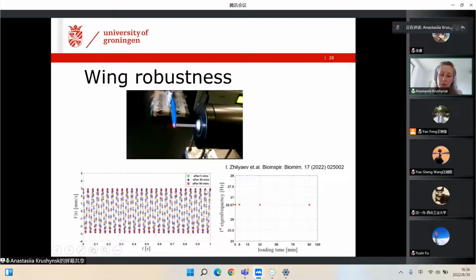exceeded 2 hours. That means that the lifetime of the 3D printed wing is comparable to that which is typically used for micro flying devices. So we can use these 3D printed wings in resonant type conditions and not expect to have any damage because of that.